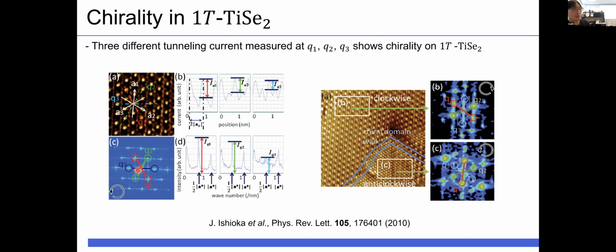So what's the reason why people could not find chirality for a long time? The answer is in the right figure. In the right figure, they measured 2 domains with domain walls between them. In one domain, the CDW increases along the clockwise direction, and in the other domain, the CDW increases along the counterclockwise direction. So because of the domain structure, macroscopically, it just looks achiral.